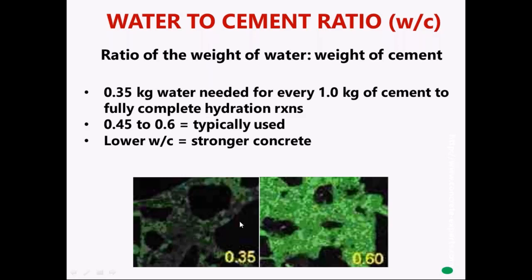So to give you an idea of what I do, here I'm showing you 2 pictures of cement paste through the microscope, but in this case I'm using fluorescent light. I can spike the epoxy with a dye that will fluoresce under fluorescent light, which makes the water cement ratio determination easier. On the left, the black objects are aggregates, and in between is paste that has a water cement ratio of about 0.35. On the right, the paste has a water to cement ratio of 0.6, about double. So microscopically, it's easy for me to see relative differences between low WC and high WC and estimate them accordingly.